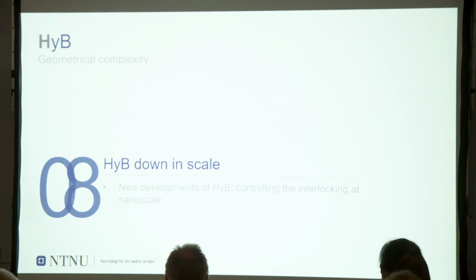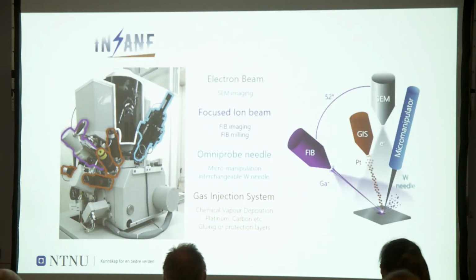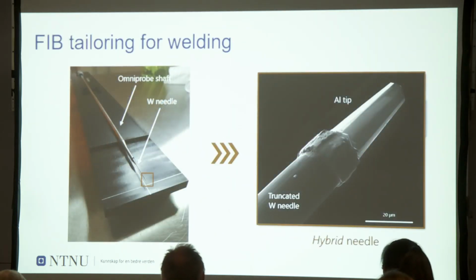But what happens if you go down in scale with ion beam? This has already been done in a project financed by the Research Council of Norway, and the project name is Insane, because none of us believed that it was possible. So we tried. The idea was to use the ion beam to reproduce welding in situ, using a hybrid needle of the FIB: truncating the real needle of the FIB and putting the filler material here to weld on the base material.